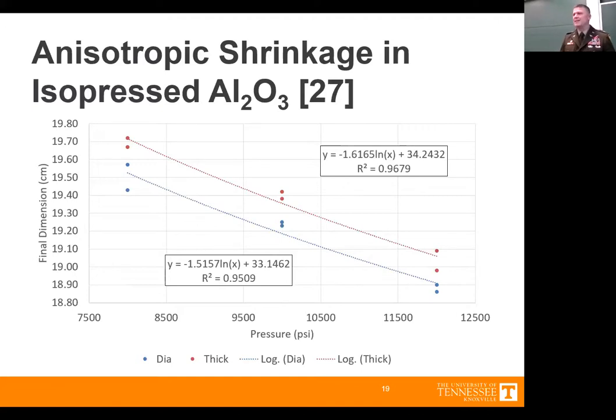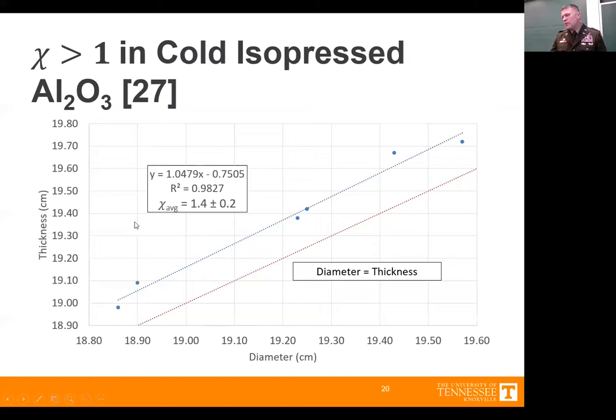Only in this case, instead of uniaxial pressing in only one direction, it was put into a wet bag and isostatically pressed equally in all directions. So here, now we see that the radial component actually shrinks more than the axial component, which, as you can predict, leads to a chi greater than 1.